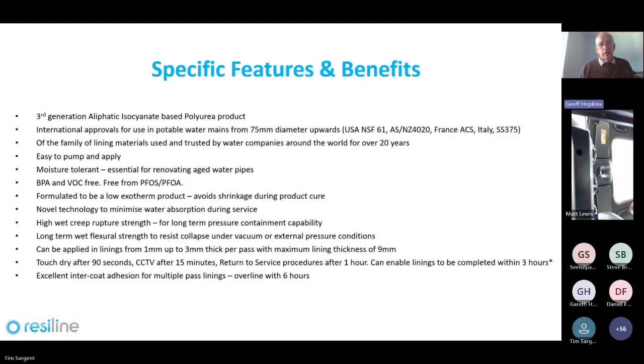The material is BPA and VOC free. It is also free from PFOS and PFOA as well. It's surprising how many times we get asked that around the world. It's been formulated to be a low exotherm product, so it avoids shrinkage during product cure. And we utilize some novel technology in the material to minimize water absorption during service, because water absorption is what kills linings. If you get water absorption, you get swelling of the product, you get debonding, you get a shorter service life. So this is specifically formulated to avoid moisture absorption.